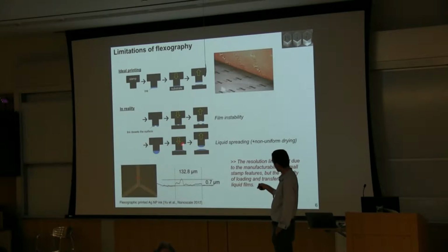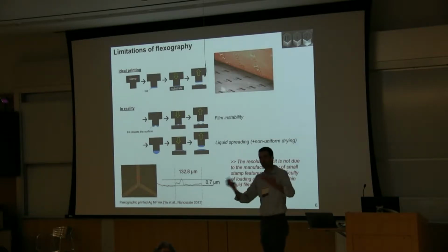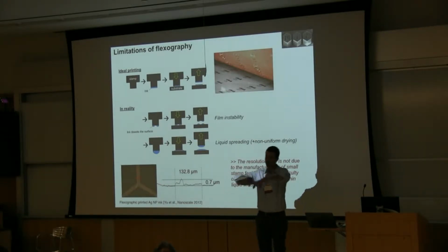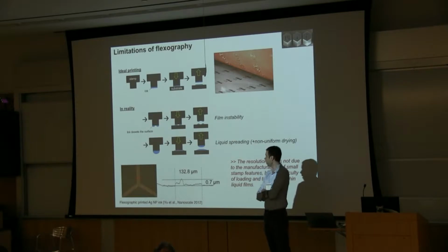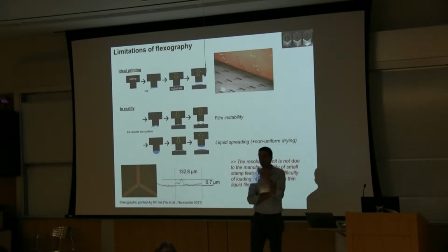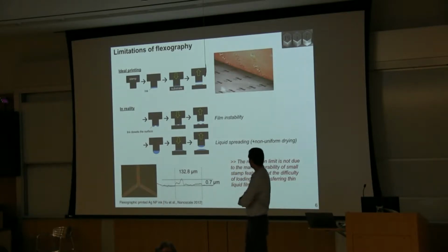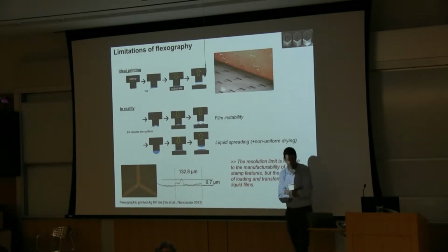Or if you overload the stamp or apply too much pressure, you have issues due to liquid spreading beyond the stamp feature, as well as what's known as the coffee ring effect. The solids in your ink spread out on drying. And therefore, even though you can make very fine rubber stamps, you can't make micron scale features because you run into these limitations of ink transfer mechanics.